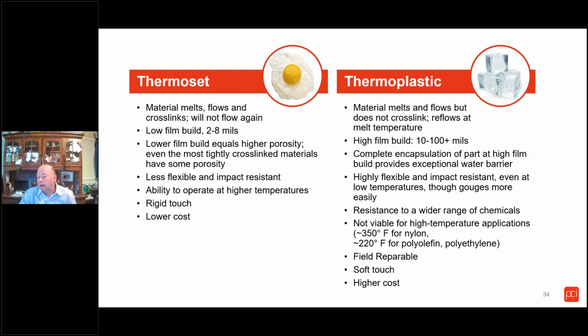They're not for high temperature applications. Nylons tend to soften around 350 Fahrenheit, and polyolefin or polyethylene coatings around 220 degrees, so they're not high temperature coatings. But in the right application—for example, buried pipes or tanks, something where you can encapsulate the part and reduce the risk that the coating will be breached—they are an excellent alternative, or option, I should say.